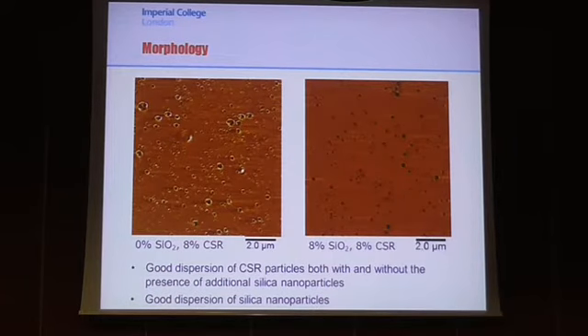So, morphology. On the left-hand side, I have a typical morphology from an AFM image of what happens when I add 8% core shell rubber particles. So we can see the CSR particles, and they're reasonably well dispersed. And then on the right-hand side, I have an image with 8% CSR particles and 8% nanosilica. So we look here, we can see some little yellow dots. They didn't come out too well on the screen, but there are some little yellow dots here, which are the silica nanoparticles. And so we're reasonably confident that there's a good dispersion of CSR particles in both the case of CSR on its own and also in the hybrid case, and also the silica nanoparticles are reasonably well dispersed throughout the remainder of the matrix with CSR in the hybrid case.